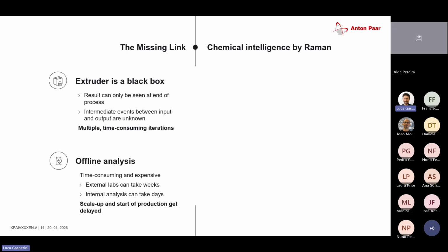So typically you have, as I said, offline analysis, which is very time consuming. Let's say I run the extruder process, then I take the sample, bring it to the lab, and do some DSC measurement, some FTIR measurement, maybe some dynamic mechanical analysis, if it's a film or any specimen in a form. Then I get an idea of how the sample behaves, and if it behaves the way I would want it to, right? But the thing is, this takes a lot of time.